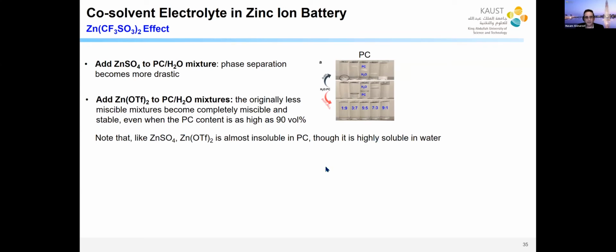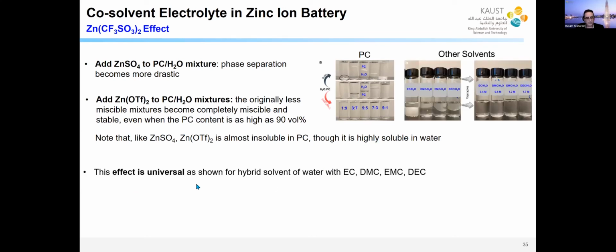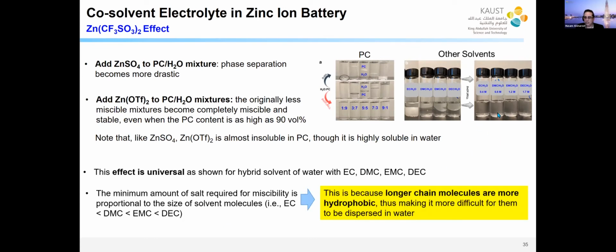So what is going on? We tried to see if this is unique to PC, but we found out this is universal. If you have other carbonates, ethylene carbonate, dimethyl carbonate, etc., when you mix them with water, they are phase separated. But you add this triflate to them, and suddenly we form these very nice and homogeneous solutions. More importantly, we also found out the amount of salt that you need to add to achieve this miscibility depends on the size of the solvent molecules. It turns out it is proportional. The amount of salt is proportional to the solvent size because longer chains are more hydrophobic, so you need to add more salt. Okay. So we wanted to understand this more.